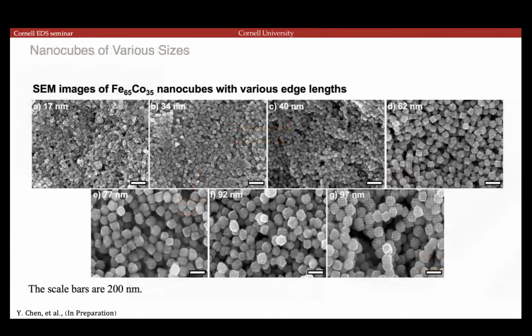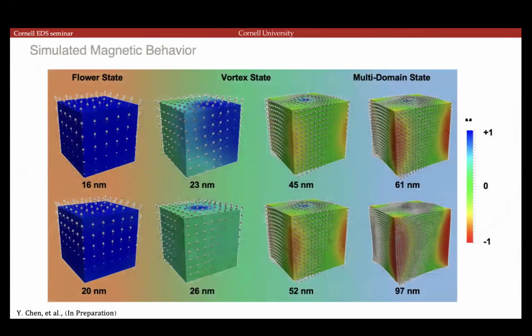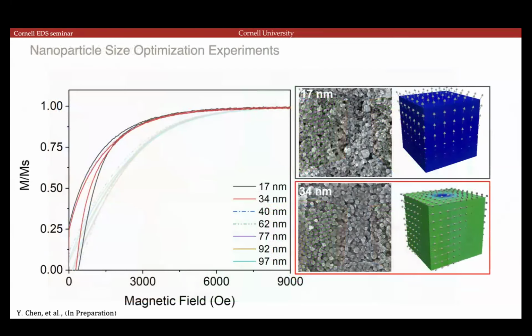And my student then compared the nanoparticles as a function of size so that we can try to identify that narrow range of particle sizes where we can get single domain behavior. If you look at simulations of the material properties, it's a very small range of sizes. So 16 to 20 nanometers based on simulation should be uniform magnetization. Anything higher than that, and the magnetization starts to curl upon itself and become multi-domain.